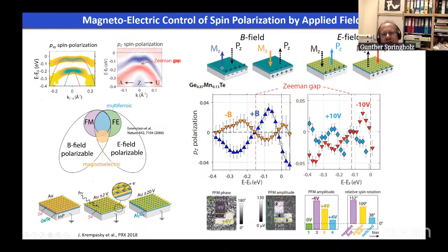Moreover, we can manipulate the magnetization direction and the polarization direction by applying magnetic or electric fields. So we have done such experiments. We measure the spin polarization, for instance, here along the Z direction. We apply a magnetic field to the system to switch the magnetization from the up to the down direction, and we see indeed the spin polarization is also switched. And likewise, we can do the same by applying electric fields to switch the polarization from the up to the down direction. And we can also see that the spin polarization is reversed by this process.